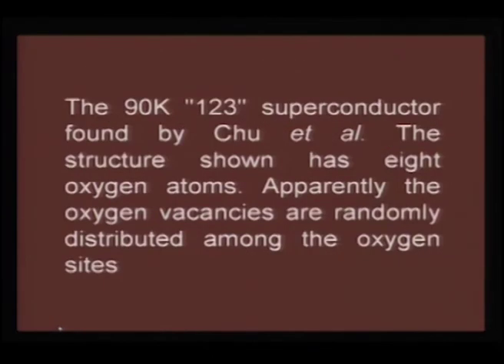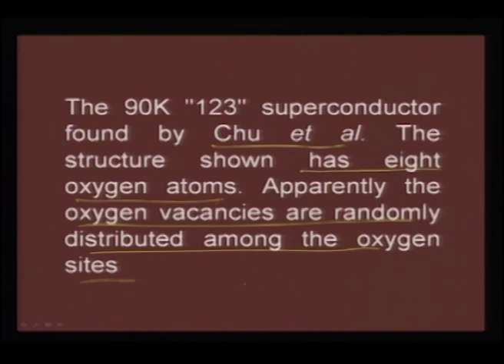The 90 K 123 superconductor was found by Chu et al. If you calculate the number of oxygen in this lattice, you would see that apparently the oxygen vacancies are randomly distributed among the oxygen sites, and this unit cell has 8 oxygen atoms, and their random occupancy, and how they can be taken out of the lattice or put inside the lattice, will determine whether this particular compound will be superconducting or not.